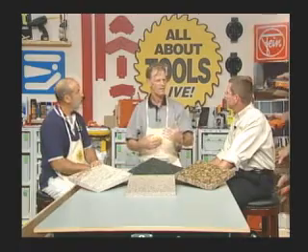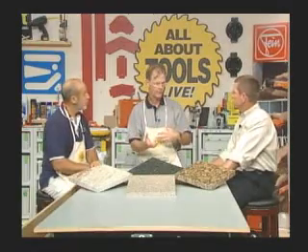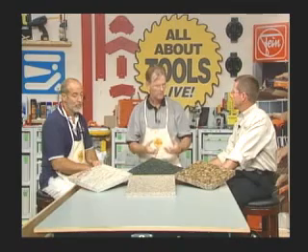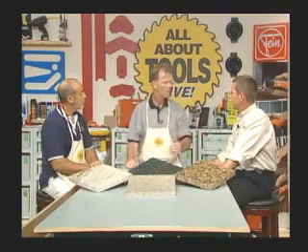Okay, and one of the things I want to move to from that, one of the things you hear a lot about stone, one of the characteristics is its porosity, the presentation of fissures. Obviously, the more dramatic the stone, the more fissures you're seeing, the greater the porosity. It's much more likely to stain, whereas you get some stones with a smaller formation of mineral crystals. They're packed much tighter. The stone has much greater density, much greater weight, and therefore the porosity is greatly reduced. Exactly. Rule of thumb, the darker the stone, the more dense, less porous it is.